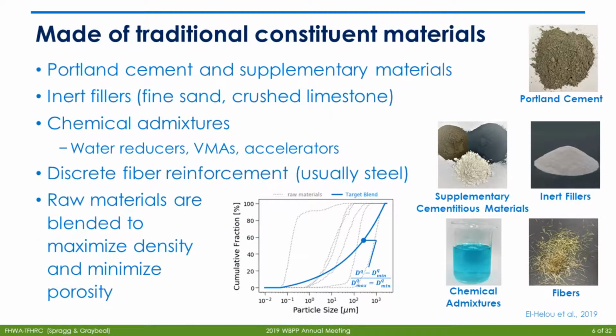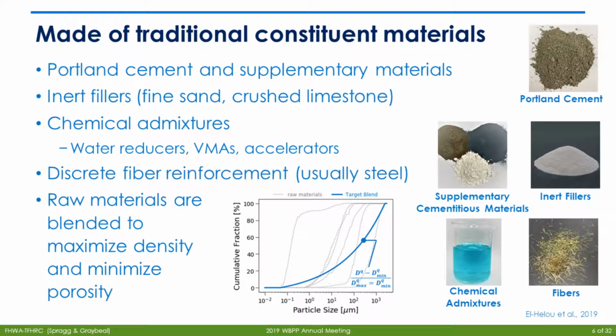Again, it's made of traditional materials, so you would recognize a lot of the materials that go into this product: Portland cement, supplementary materials, fillers, and then admixtures and fibers. The real special part of these materials comes in how they're blended together. They're blended to try and minimize the porosity. If you could imagine a volume distribution of sizes along the bottom, we have different particle sizes. We blend these together to try and make an optimized gradation to minimize that porosity.